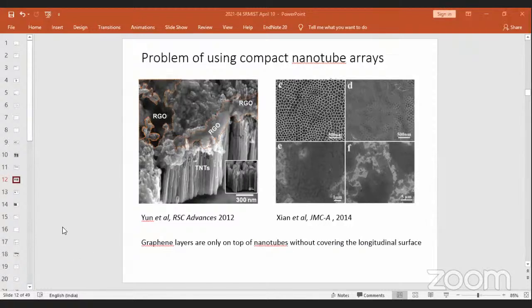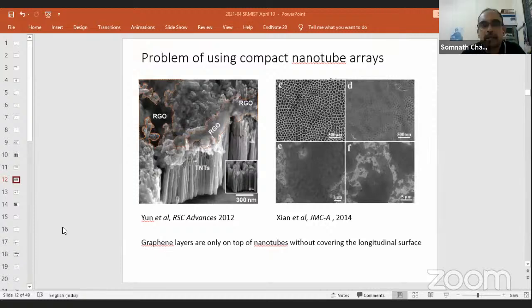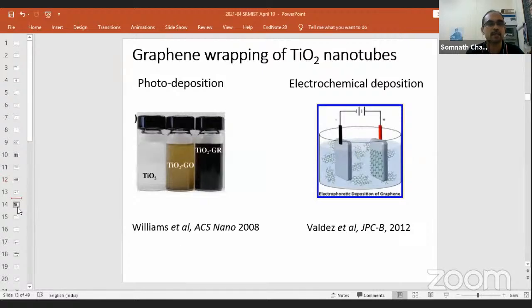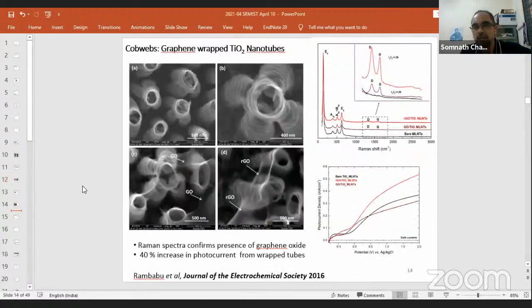So then the TiO2 nanotubes, when we looked up the literature, we found there are a few papers in 2012, 2014 on TiO2 graphene. But all of them had the problem that they had taken compact nanotubes where graphene cannot go to the side of the nanotube. As you can see on this slide, graphene layers are only on the top of the nanotube. So that was our first challenge. I'll start skipping some slides, standard practice when I'm running short of time.